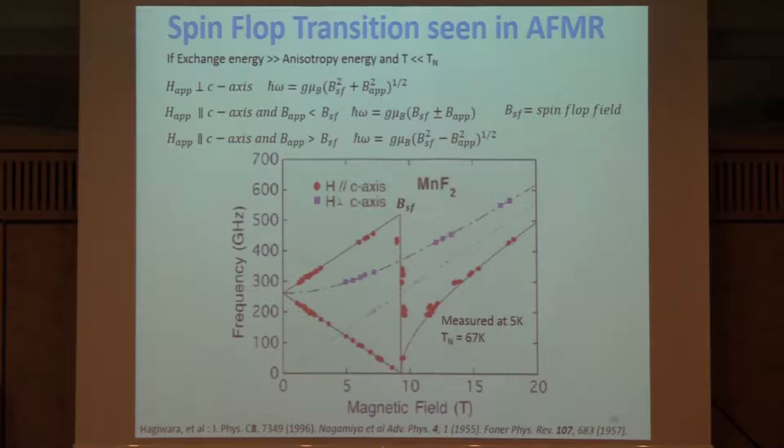I made these slides available, but you might want to have a look at this paper here. It's not published in a very prestigious journal because it's dotting I's and crossing T's, but it's just an example of a really, really nice piece of experimental work. Because this is now antiferromagnetic resonance, but showing the spin flop transition. So now, if you start off at zero applied field, if you could detect it, you'd have a mode. And as you increase the field, the energy of that mode increases. Sorry, that's if you're perpendicular to the easy uniaxial axis. If you're parallel to the easy axis,